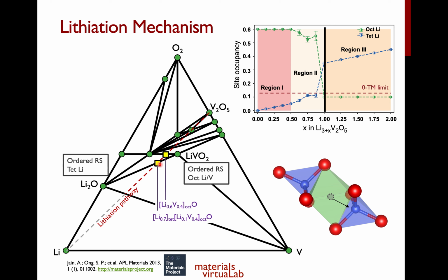If we look at where Li4V2O5 is, it is actually sitting on this tie line between Li2O and LiVO2, right? In LiVO2, this is our standard layered crystal structure, which is essentially an ordered rock salt with octahedral lithium and vanadium. And on the other end, you have Li2O, which is an ordered rock salt. Again, you can think of it as an ordered rock salt with all the tetrahedral lithium occupied. So when you hit this Li4V2O5, there is a sudden driving force for lithium to get into the tetrahedral site. In other words, it is trying to become more Li2O-like. Your lithium occupancy in the octahedral site drops to about 0.1. Your vanadium never changes, so your vanadium is always in the octahedral site. And now you are starting from a much higher occupancy of lithium in the tetrahedral site. So this is a redistribution of lithium, right?